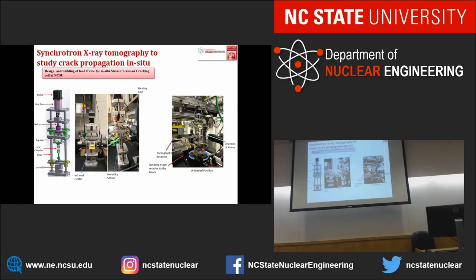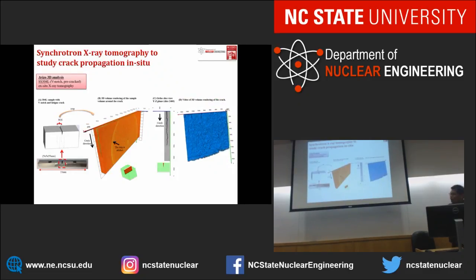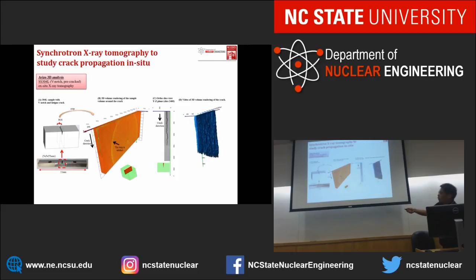Combining this tensile machine with the X-ray beamline, we can get data as tomography. As you know, the difference between diffraction and tomography is that tomography is more like an imaging technique, which can give you a 3D visualization of your sample. Here, we tested some stainless steel which had been pre-cracked at NC State by fatigue, and the tomography data generate a 3D reconstruction of the shape of the crack.